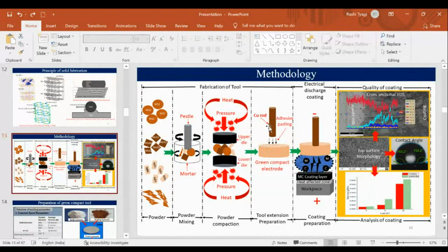So after making the green compact tool, we paste it onto another conductive rod. Why? Because this tool has a limited size, so it cannot be directly put in the machine. There's some limitation. So we use the copper rod and attach it to the green compact tool, so that we can deposit the green compact material over the workpiece surface.